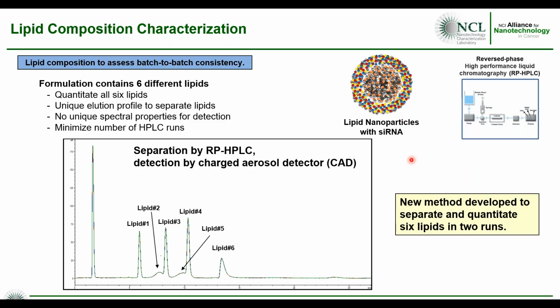So first with lipid composition. Our client came to us with lipid nanoparticles with siRNA loaded, and we wanted to assess batch-to-batch consistency. So for this, we developed an HPLC method with charged aerosol detector, or CAD, and we came up with an elution profile that can actually separate out the 6 different lipids. And there are no unique special properties for detection, so we had to use CAD in this sense. And with 2 runs, we can actually quantitate the 6 lipids in our formulation and use this to assess batch-to-batch consistency.